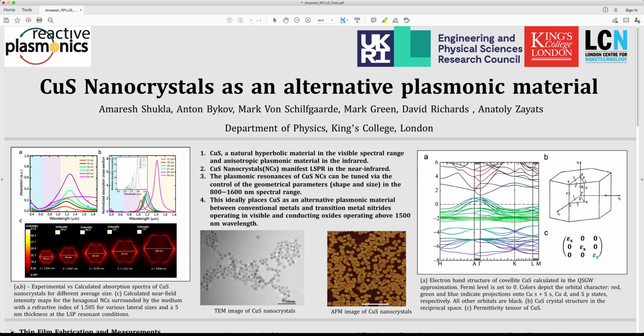These properties include a natural hyperbolicity in the optical visible spectrum, while at the same time also being anisotropic and plasmonic in the near infrared. Subsequently, these nanocrystals show a dominant localized surface plasmon resonance in the near infrared, which has been demonstrated to be